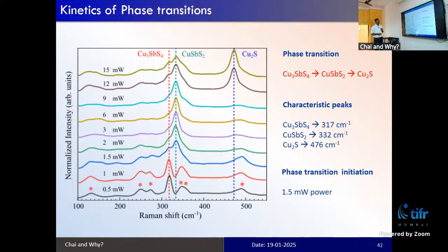Further, we tried to observe the kinetics of the phase transition in this material. As I showed earlier, this is a power-dependent Raman spectroscopy in which lower power gives Cu3SbS4. At higher power, you get a phase transition and you get CuSbS2. At much higher power, you will get Cu2S.